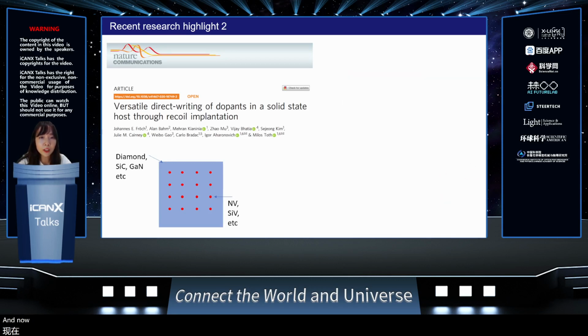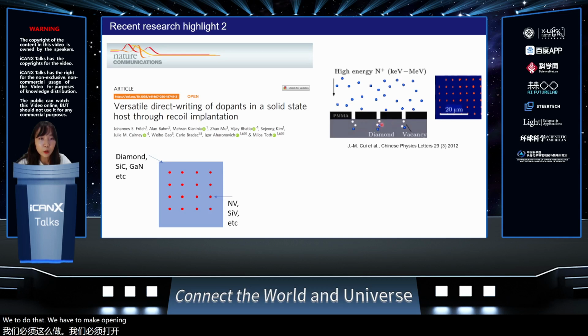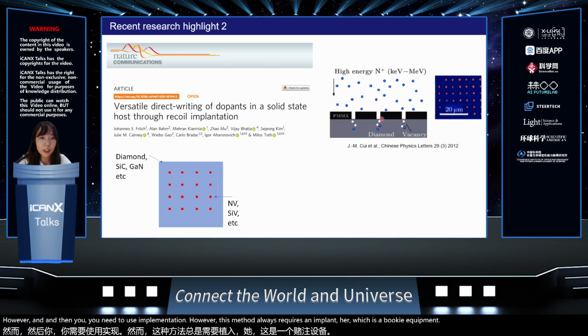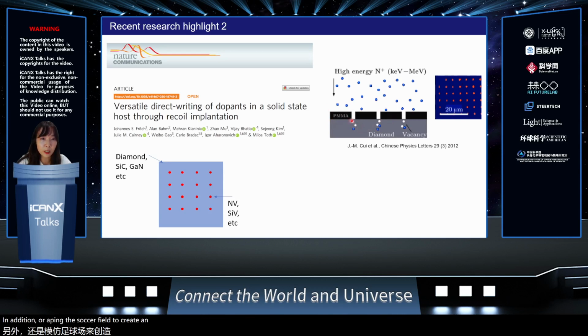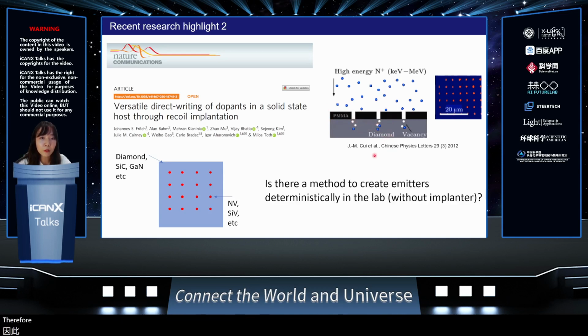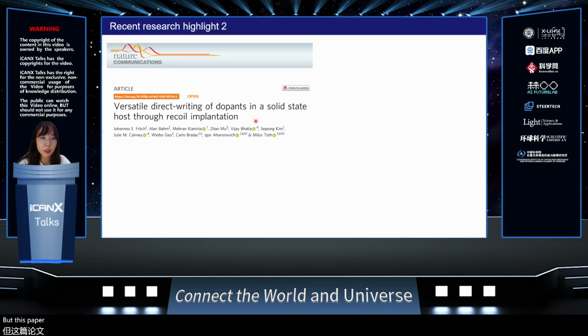And now moving on, how can we use this implantation method to create emitters in such an array? To do that, we have to make openings using PMMA, for example, and then use implantation. However, this method always requires an implanter, which is a bulky piece of equipment, and additional e-beam lithography to create an opening in PMMA. Therefore, our research question was, is there a method to create emitters deterministically in an array in the lab without any implanter? So this paper shows the answer to that question.